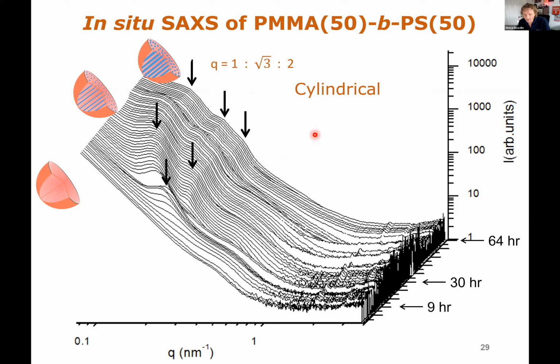And these we can then take and calculate. Looking at the Q number that comes out of this, we were able to understand that these were showing us that the structure we were forming was cylindrical. And you can also, from this, calculate that the domain size that you are forming should be of the order of 25 nanometers.